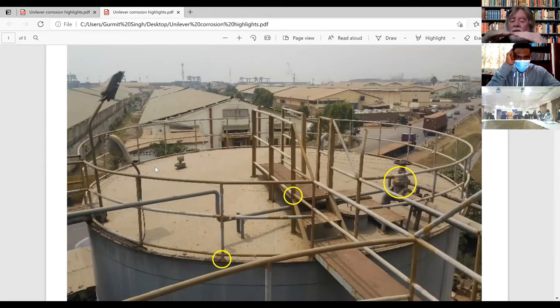You've got your metals welded together, which are the same metal, but the weld metal is different, and that's why you get a reaction, and it forms a little corrosion cell. It starts corroding. So they're the areas that always start corroding first, and that's why these areas are critical. When you're blasting, you blast the structure as normal, but these areas you've got to pay a lot of attention to, all welded areas around flanges and so on, and also things like bolt heads where they've bolted. You've got to blast all the way around and around the washers, everything, before you coat. So I've just ringed off some key areas.